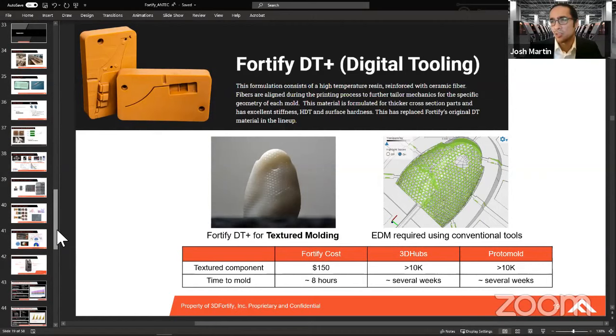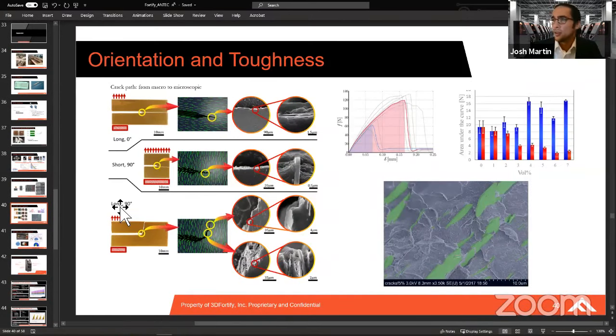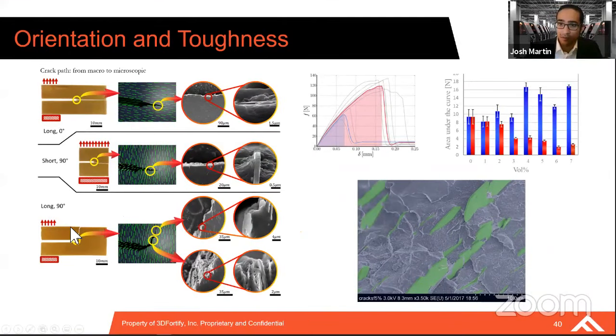From stress concentrations, this might be a good slide to speak to. There's a lot of very interesting fundamental science that we're pointing out, and with our collaborators at Northeastern University, forgive me, I did not add their reference here, we're seeing this really impressive ability to improve toughness, which leads to how do you mitigate against residual stresses, against micro cracks from growing, and how do you make your parts more robust? And this is what we believe is one of the main reasons why our printed tooling outperforms some other options, because these aligned fibers will effectively stop cracks from spreading and lead to more robust materials.